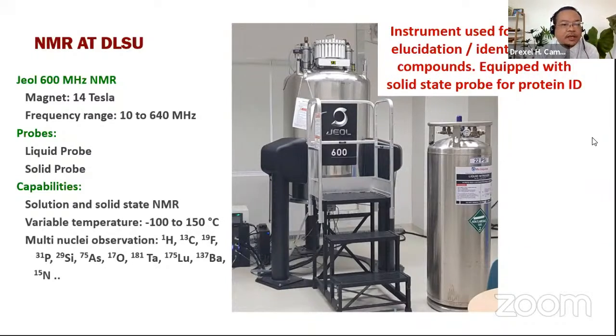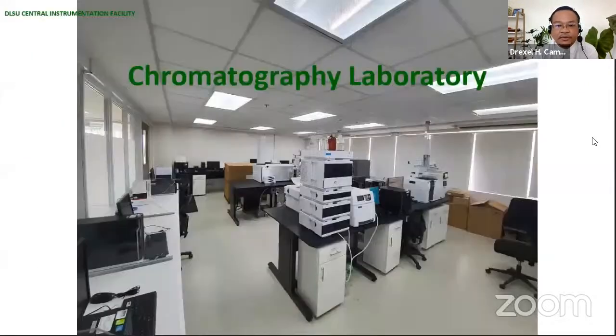So the NMR at DLSU is a 600 megahertz NMR. And we have two kinds of probes, the liquid probe and the solid probe. That means we can analyze samples in solution and in solid. And we can do variable temperatures from -100 to 150 degrees Celsius. And we can do multi-nuclei observation. Aside from the usual proton and carbon NMR, we can analyze fluorine NMR, phosphorus, silicon, and so on. Okay, so this is the instrument necessary for confirming the structure of your compound.